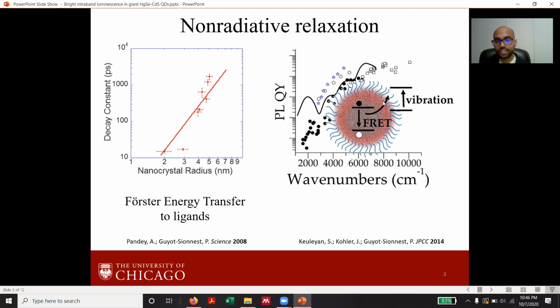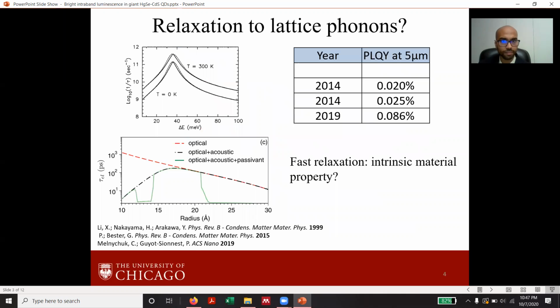More recently, Sean from our group studied the fluorescence quantum yield of mercury telluride quantum dots at different frequencies and showed a remarkable agreement of the model with the experimental quantum yields. Though there is a great agreement at shorter wavelengths, the measured quantum yields are 1 to 2 orders of magnitude lower than the calculated quantum yields at 5 microns. So this led us to consider other mechanisms of relaxation.